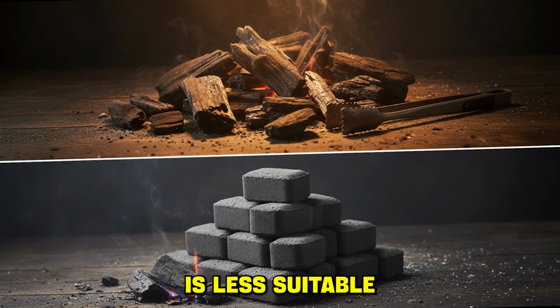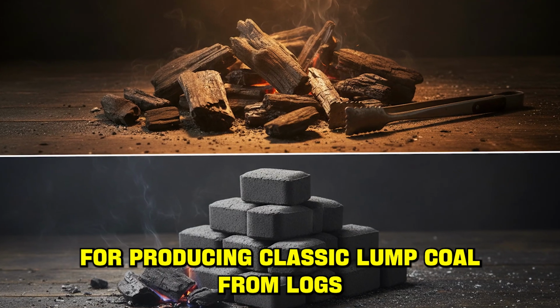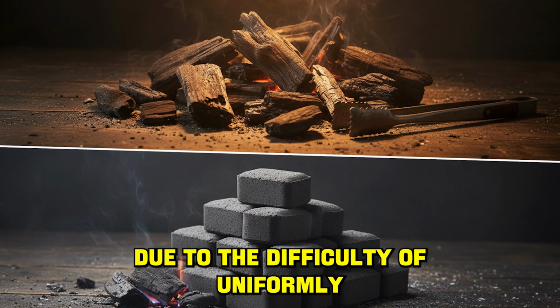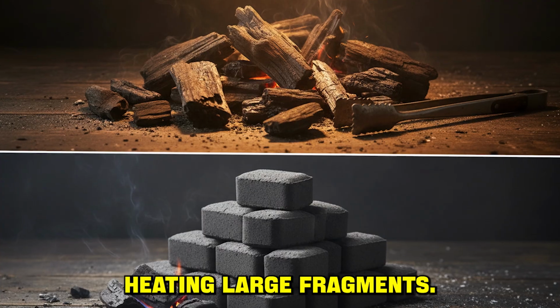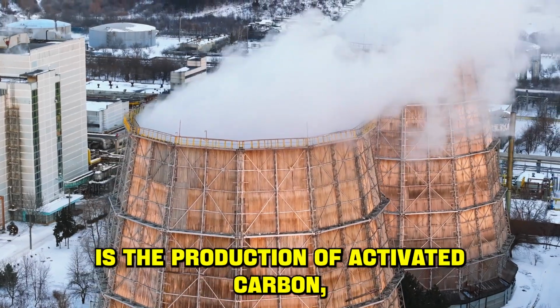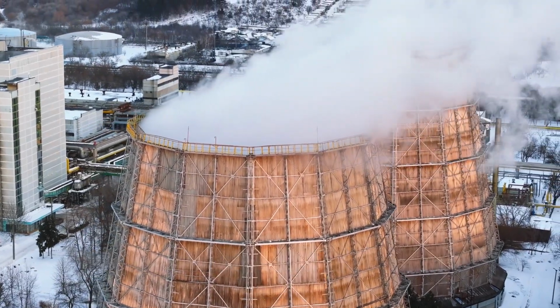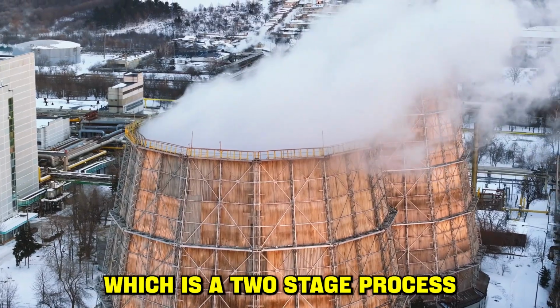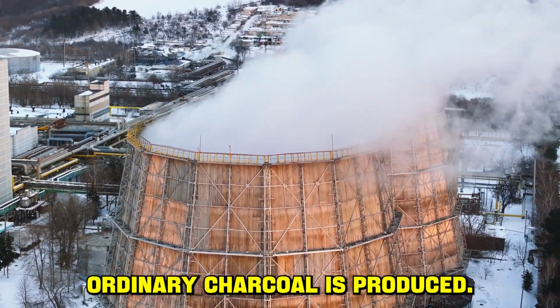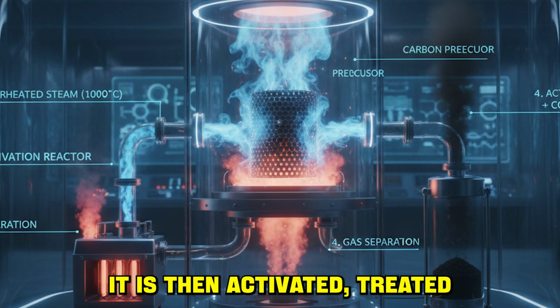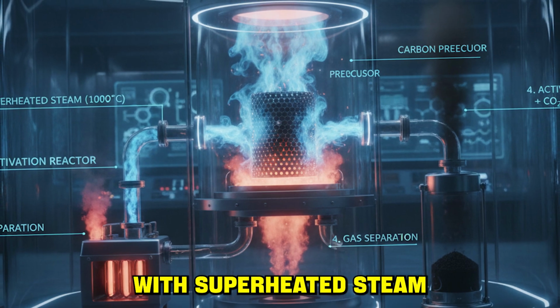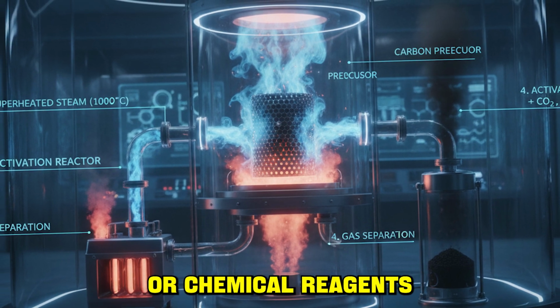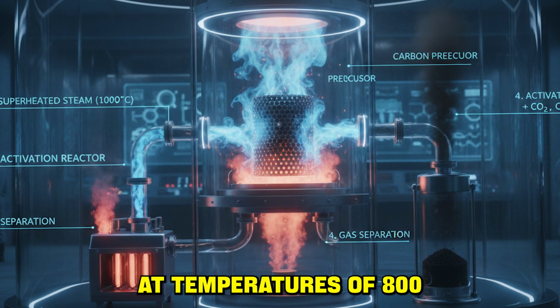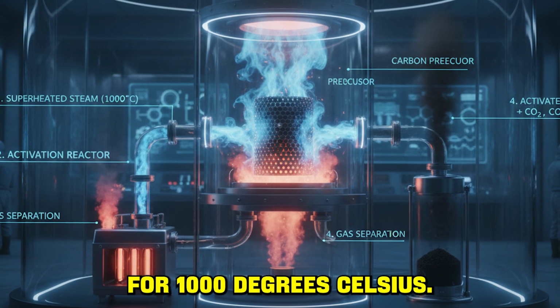Continuous production is less suitable for producing classic lump coal from logs due to the difficulty of uniformly heating large fragments. A separate area is the production of activated carbon, which is a two-stage process. In the first stage, ordinary charcoal is produced. It is then activated, treated with superheated steam or chemical reagents, at temperatures of 1000 degrees Celsius.